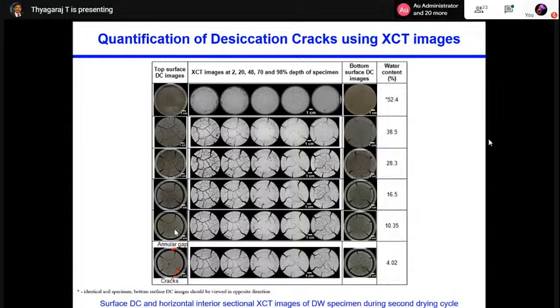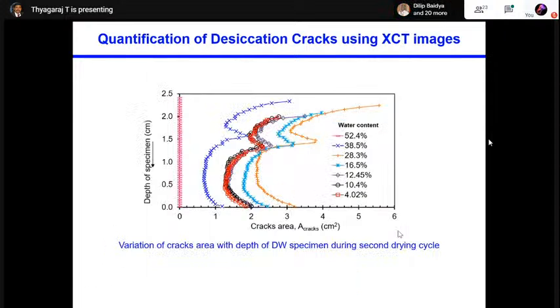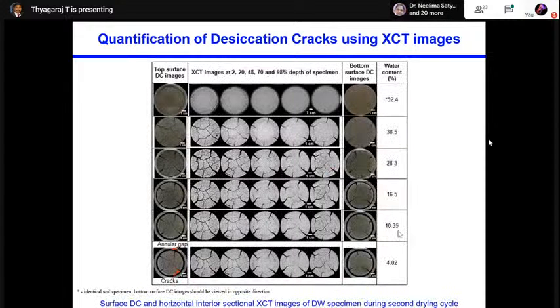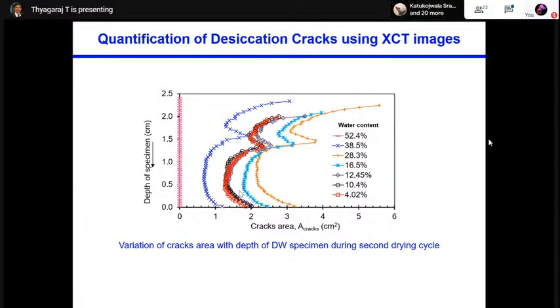When you see these last two rows, the crack pattern is almost the same. Once it has reached the shrinkage limit, after that there is not much change. When we took this specimen and measured it through the image software, the area of cracks, we plotted it like this with the depth of the sample. You can see that the crack area at the beginning is 0.